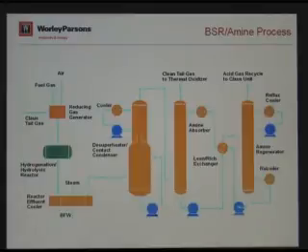Is there any absorbent that can absorb the SO2? If any leftover SO2 in the range of ppm, we capture it at the bottom of this tower with caustic. Because if SO2 gets to this amine, it contaminates the amine. We cannot have SO2 in the amine. You have to throw away the solvent. It just degrades. We call it degraded amine. You have to dump the equipment, empty everything, and bring in fresh amine if you have a breakthrough.